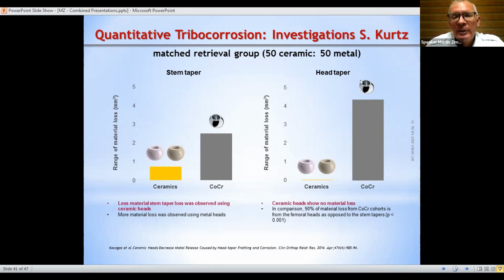If you look now at the taper of the head, this is the big difference. There's no material loss coming from the ceramic because it's so hard. There's no possibility for a titanium stem or cobalt chrome stem to abrade the surface of the taper of the ceramic. But on the contrary, if you have a cobalt chrome head, then you have a big quantity of loss of material. And in this case, remember, the loss of material that you have with cobalt chrome creates typically this problem of chrome ions, chrome particles, or cobalt ions or cobalt particles in the body of your patient. So we demonstrate here that by having a ceramic component, you have much less material loss than having a cobalt chrome component.